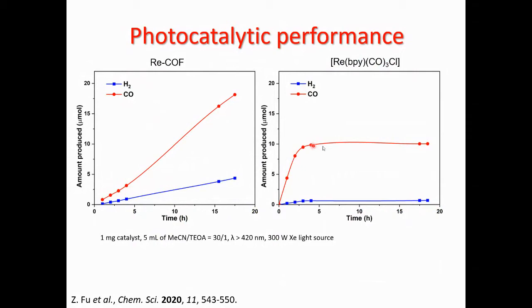So after a few hours' time, it is actually inactive. And this is really a known thing in literature as well. For our network material, because we're able to distribute the rhenium centers within the material, we're able to really protect these active sites much more. We can see we have much more steady carbon monoxide evolution over time in these materials. The materials also produce a small amount of hydrogen, but it's really not a lot, and much less than the previous first generation materials that contained palladium, which produced large amounts of hydrogen.